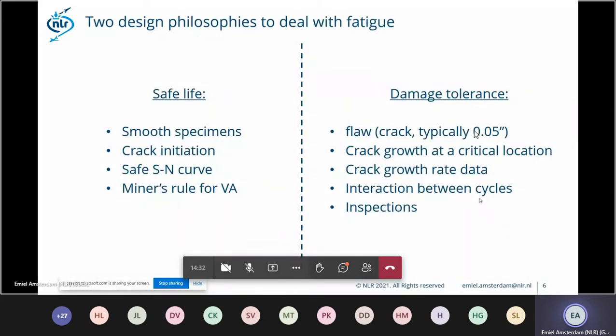So how do we deal with fatigue in conventional design approaches? We can use safe life, or we can use damage tolerance. Safe life, I think one of the first design methodologies, where you usually look at crack initiation, and if the crack has initiated, then that's the end of the life of the component. You use some kind of safety factor to ensure the part doesn't fail in service, and from the mean life of the SN curve, you create a safe curve for the design. You typically use smooth specimens to determine the SN curve, that's the cycles versus stress curve, to design the component, and the miner's rule is used for variable amplitude fatigue.